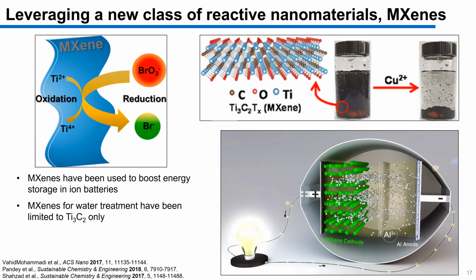So here are two studies using titanium carbide MXene materials. And you can see here in the top left, this study suggests that you could use titanium carbide MXenes to reduce bromate to bromide. And you can also use the same material to adsorb and reduce copper ions in water.